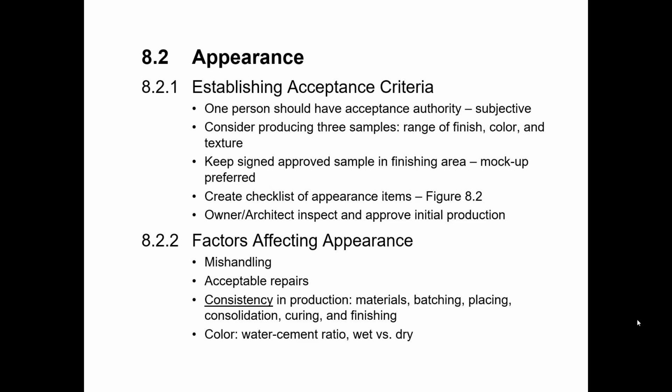Cement and water, the only variation being the water cement ratio. And you can see from a 0.3 to a 0.6 how drastically different those two are. It's night and day, literally. Almost black, and I understand this is grayscale, to very close to white, just from going from one end of the spectrum to the other on the water cement ratio.